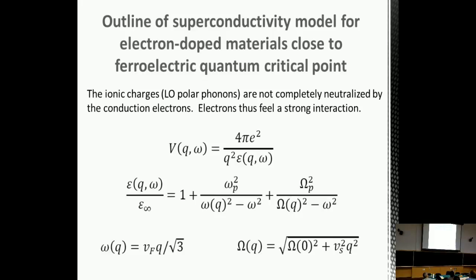frequency, and this is the dispersion of the low frequency plasmons, given here as a linear dispersion where Vf is the Fermi velocity. And then capital Omega p is the longitudinal optic phonon frequency. And omega of q here is the transverse optic phonon frequency, which disperses like this. So close to the ferroelectric quantum phase transition, the gap here in this spectrum goes to 0, and that's where you would have a ferroelectric quantum critical point. And all these parameters are known from independent experiments, so that everything here is well defined.